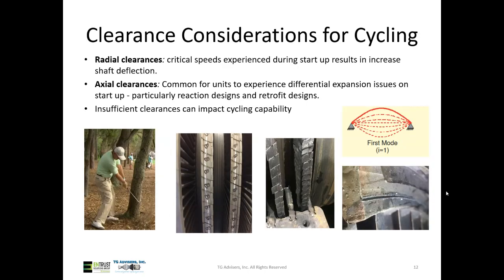All right. We also have to be worried about clearances. So when you're going through an outage, sometimes there's a desire to make clearances very tight again, particularly radial clearances, to try and get as much performance as possible, to limit the leakage in areas that don't contribute to power production. However, that can present significant challenges with cycling.